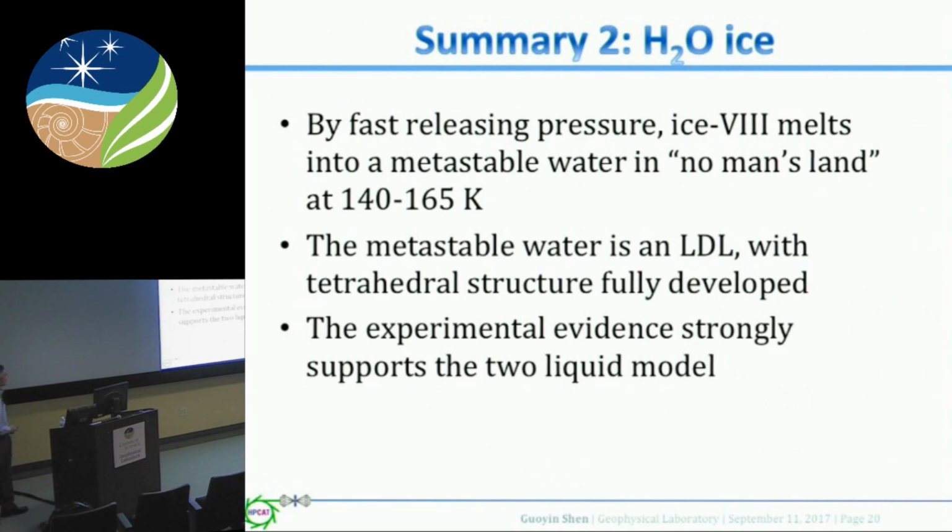So this is the summary for the H₂O part. By fast releasing pressure, the ice 8 phase melts into a metastable liquid in no man's land in this temperature range. The metastable water is a low density liquid with tetrahedral structure fully developed.